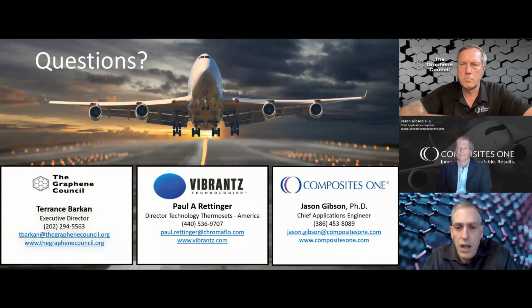These are some of the variables that can affect it. And the other thing is, you can really get a very significant amount of performance, as he's noted, at very low loadings from the use of the graphene, so that you actually get a bigger bang for the buck from using graphene for your end molded part than you do just from using, in theory, the neat resin by itself. That's a point I kind of wanted to throw in there.